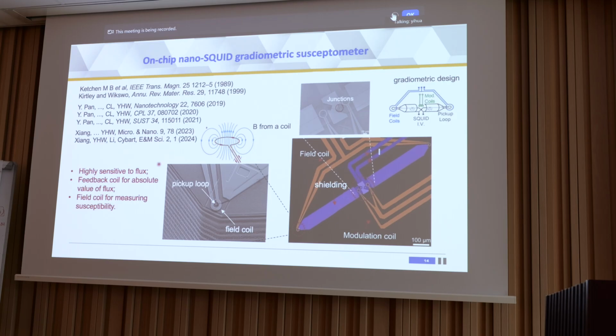And so the benefit of having this kind of design is, besides the high flux sensitivity, we can perform feedback operations so that we can obtain the absolute value of the flux, which is super important for determining the exact value of the flux. We also have field coils for measuring susceptometry so that we can determine the superfluid density through diamagnetic measurements.